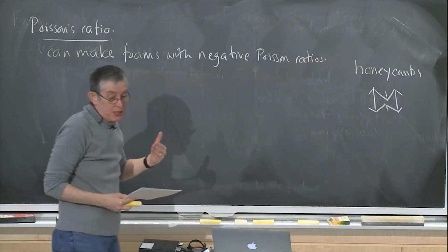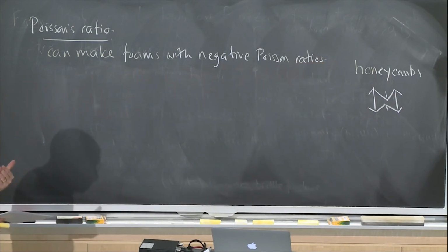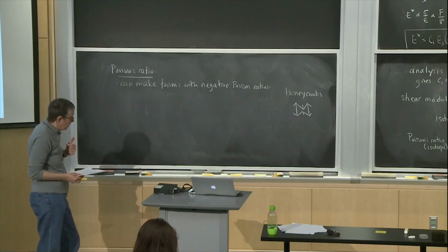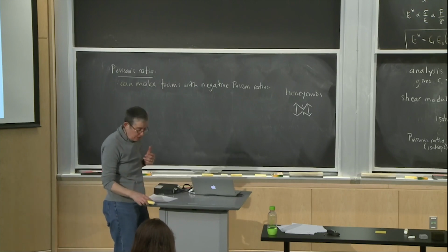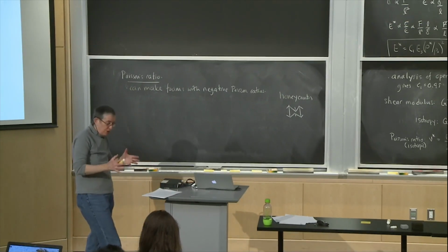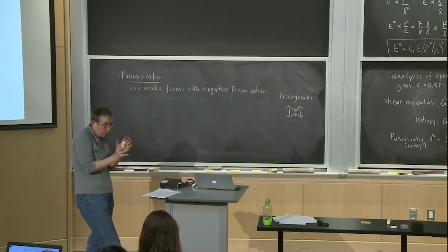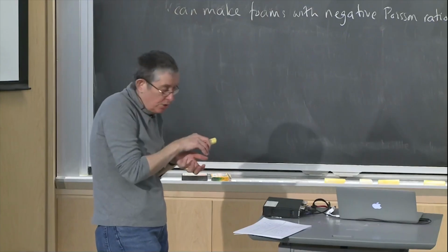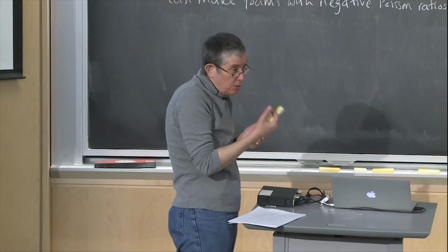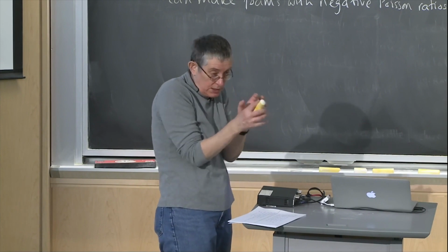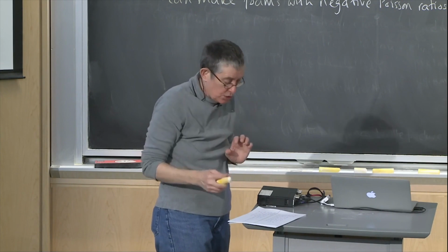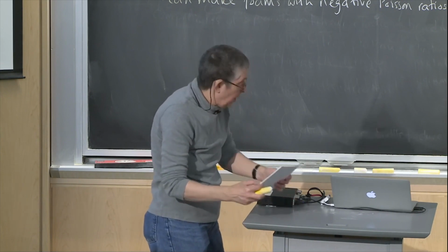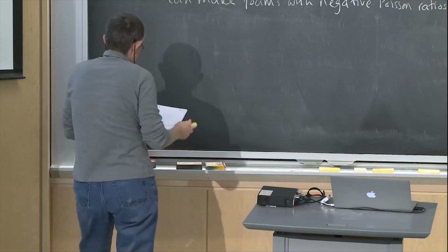So we said that theta was negative for the honeycombs. And if you invert the cell walls on a foam, you also get negative Poisson's ratios. The way they do that is they take a thermoplastic foam, and then they load it hydrostatically. So they compress it in all three directions, and they sort of smush the cells in on each other. And then they heat it up to a temperature above the glass transition temperature while it's still smushed, and then they cool it down. So they end up with that structure kind of frozen in. And if they do that, they get a negative Poisson's ratio.